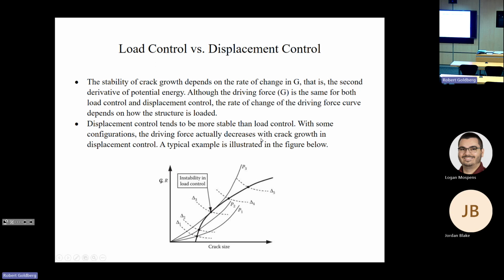So a little more on our discussion of the R curve. It's load control versus displacement control. The stability of the crack growth, as we talked about, depends on the rate of change of the strain energy release rate, which is the second derivative of the potential energy. And this driving force is the same for both load control and displacement control. The rate of change of this driving force depends on how the structure is loaded. And displacement control tends to be more stable than load control.